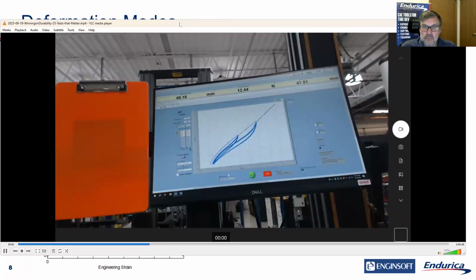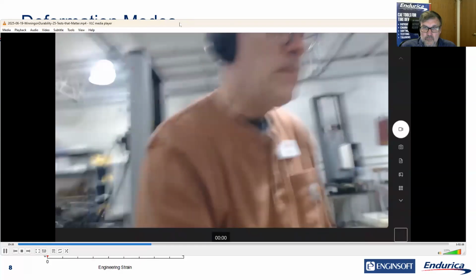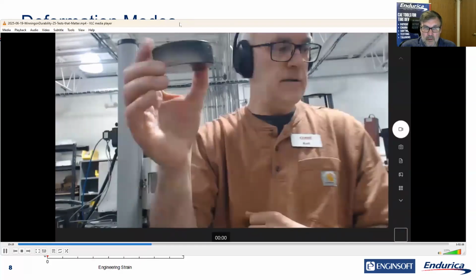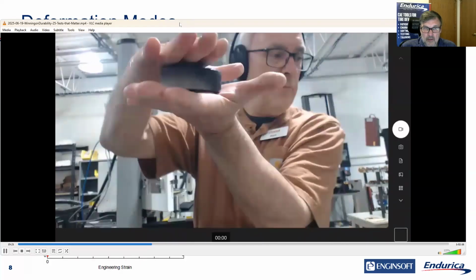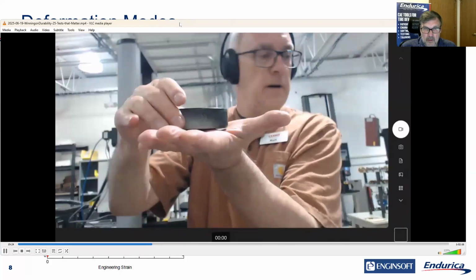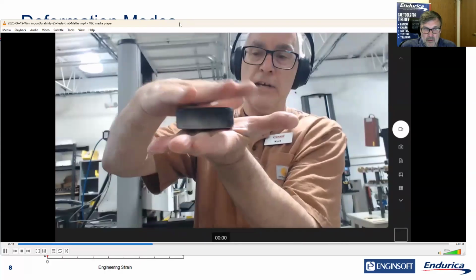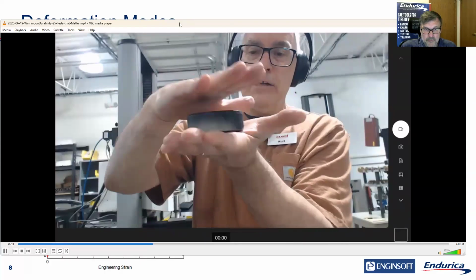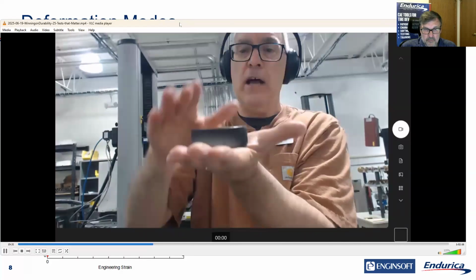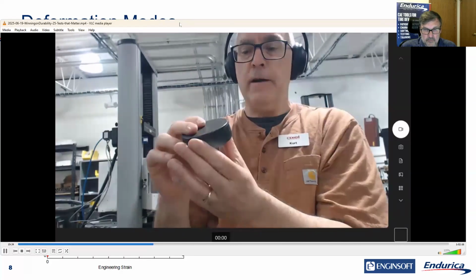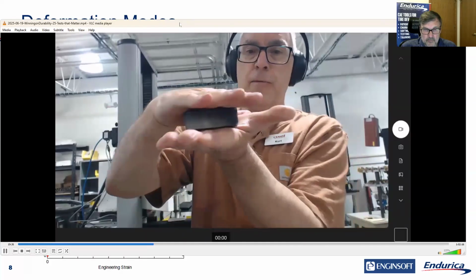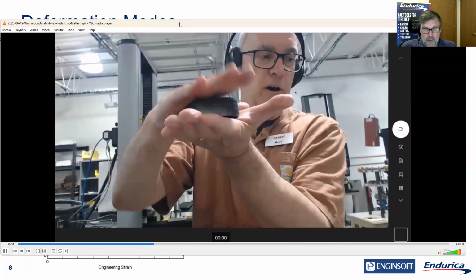One very important state of strain is compression. You'd say, hey, my part is always in compression. Yet, when we try to do compression experimentally in the laboratory, it just doesn't work. If you imagine this is a hockey puck, if I compress this hockey puck, the sides move out. But unfortunately, between my hands and the hockey puck, there's friction. And so when I compress it, it kind of bulges, and that makes a big mess experimentally. So it's not perfectly just compression. It's compression with some shearing and some other messy business.